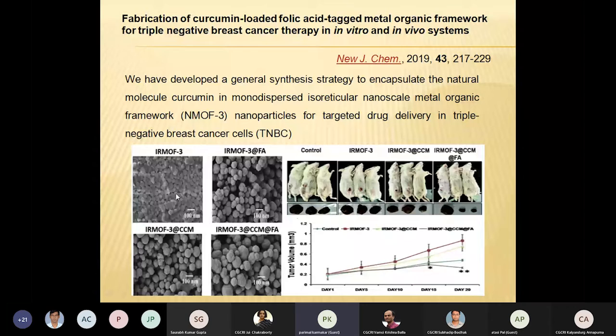As you can see in the same picture, we gradually modify the metal organic framework so that the folic acid can be conjugated, and then we use the curcumin, and curcumin can also be loaded. So these three are the first picture, and then additionally we recombine this. So we add both folic acid and curcumin simultaneously, and then you can see the structure is a little bit higher. And this has also been tested on different cancer cell lines, and we also explored the molecular mechanism, and we have seen that the curcumin could specifically induce apoptosis in the cancer cells, while in the normal fibroblast, at the dose we use, it cannot do anything, or even if it does, it's not really significant.